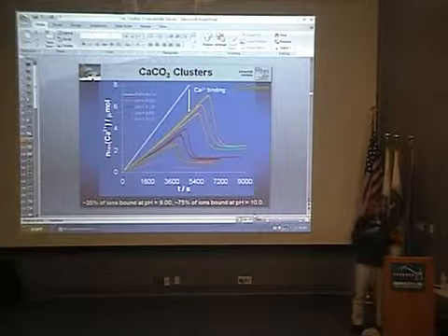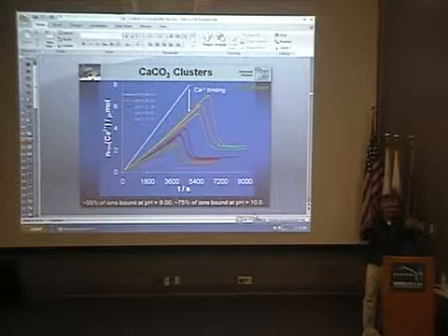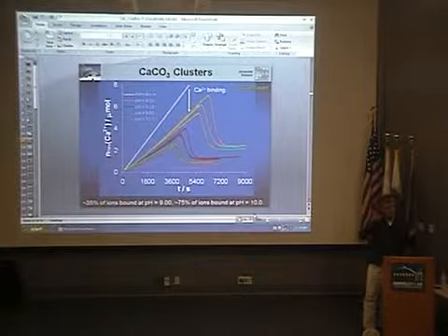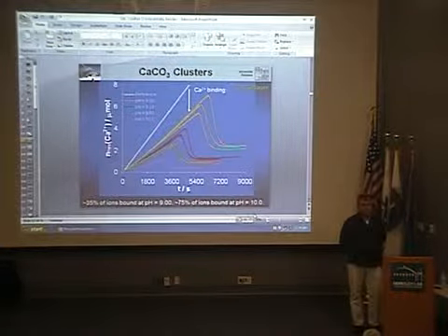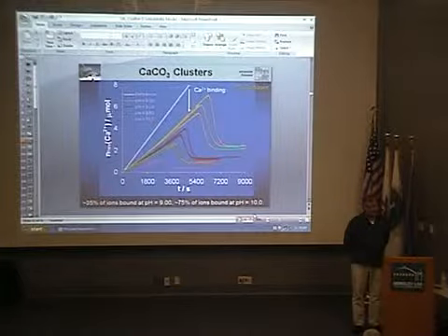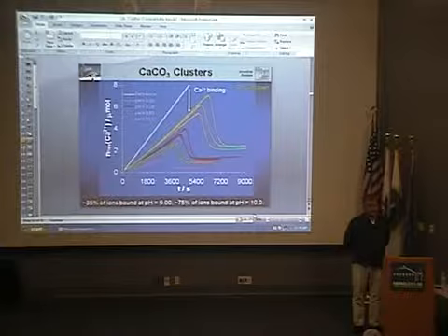This you deduce from the small equilibrium constant by saying I got more ion pairs than clusters, so that means the constant is smaller than 1, and that means the energy must be higher. Yeah. So they're stable in the thermodynamic sense that there's always a population there. Yeah. But any one of them is higher energy than the ions. Right.